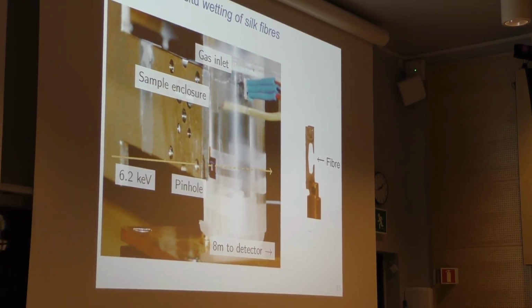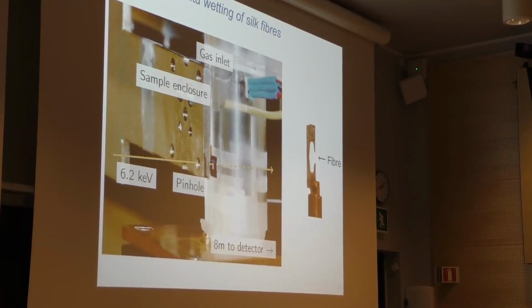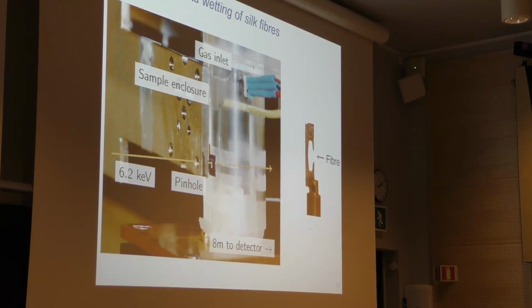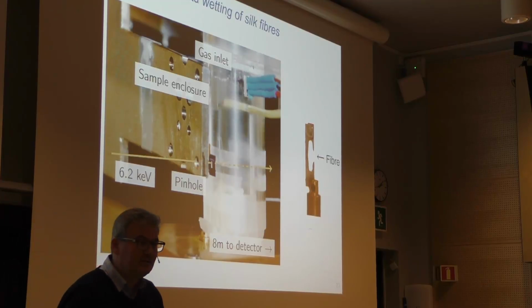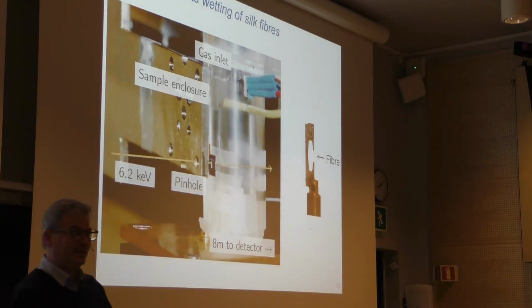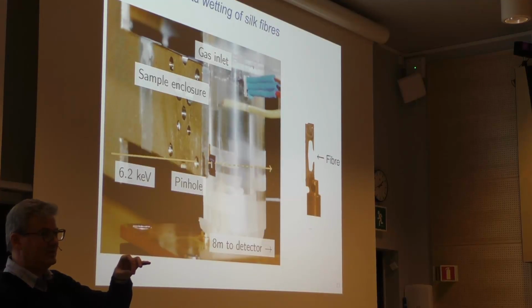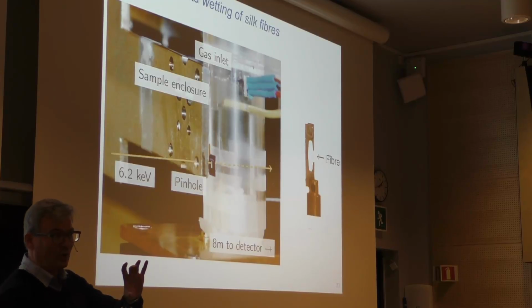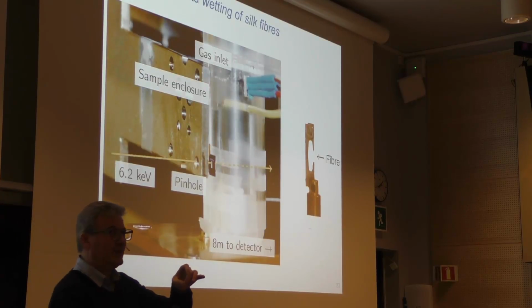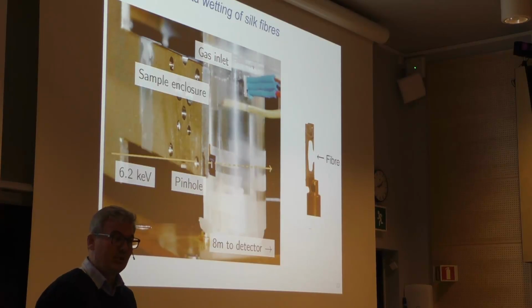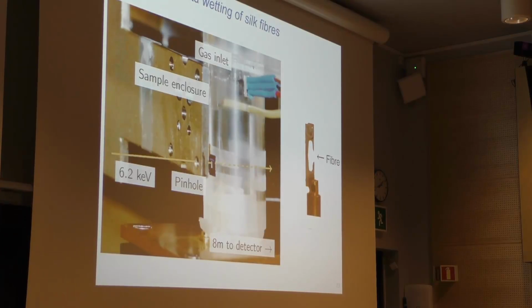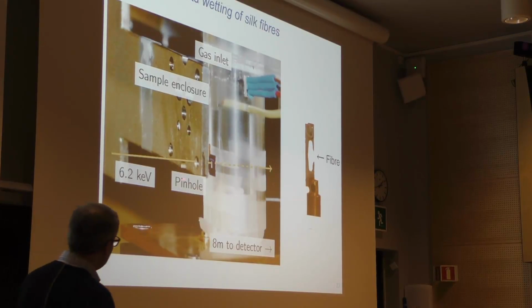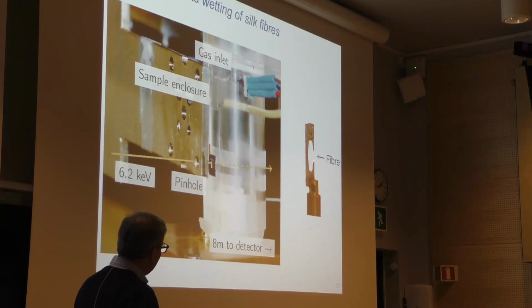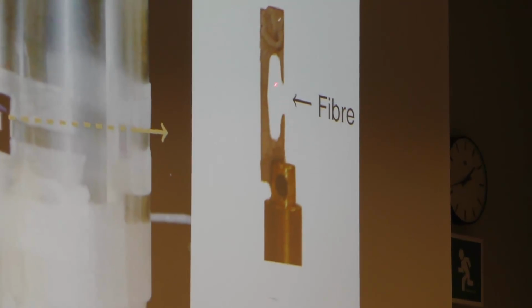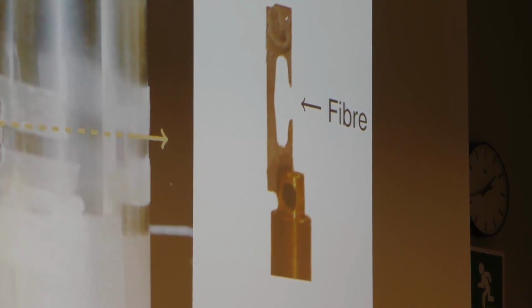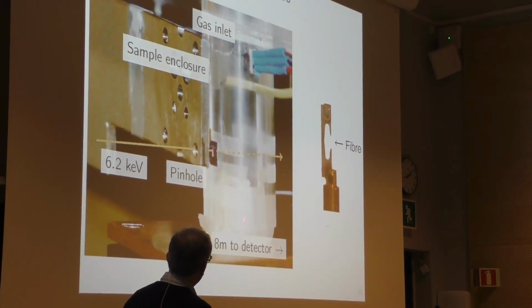So the first example that I want to show you in this regard has to do with the in situ wetting of silk fibers. And the wetting of silk fibers has been known for millennia, right? Probably that if you expose silk to water, the water will be absorbed by the silk fiber and it will expand. But to the best of my knowledge, nobody else has looked at this in situ before. So the way that we set out to do this was that we designed a holder like this and mounted a single silk fiber across here. This was then put into an enclosure, like you can see here.